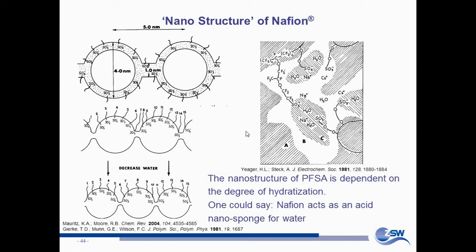Now you do the very same thing. You take this polymer electrolyte, you throw it into water of temperature about 80 degrees, take it out, blot it dry, throw it on the balance. What happens? Doesn't change? It loses weight. So the characteristics of water in these polymer electrolytes change with the degree of hydration.